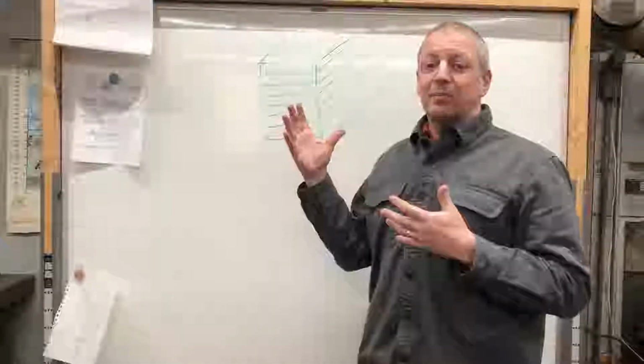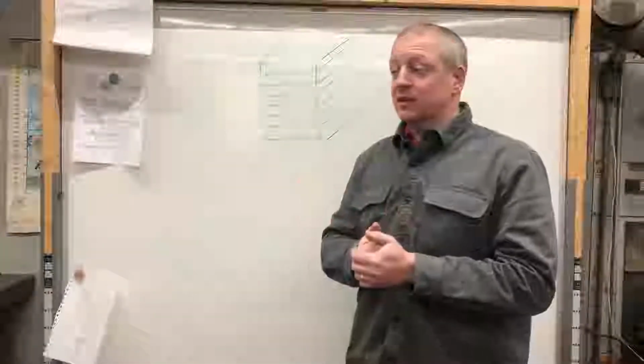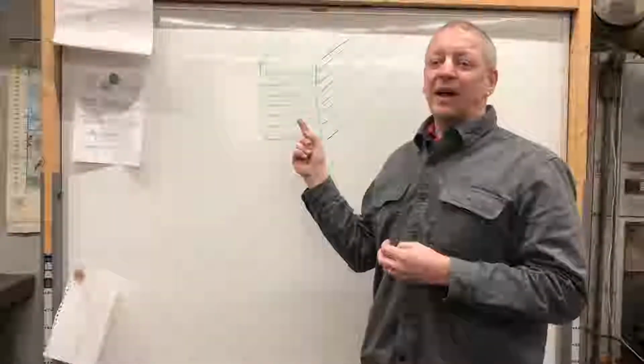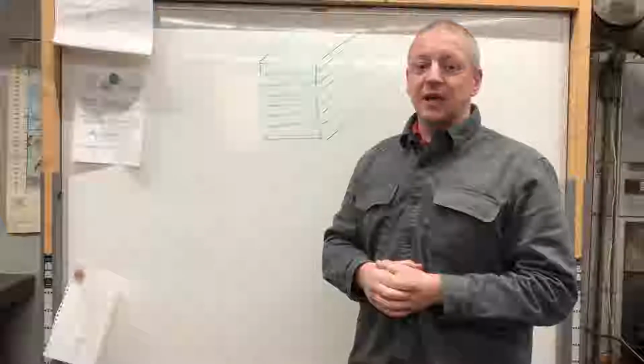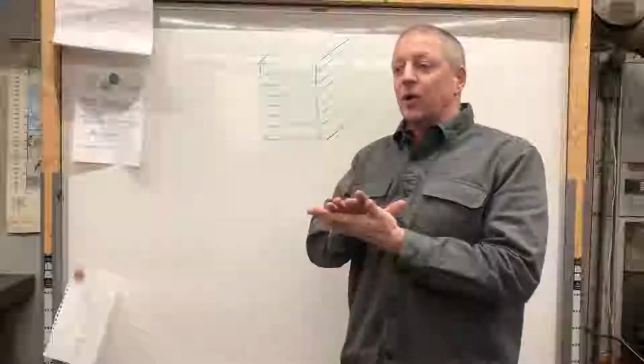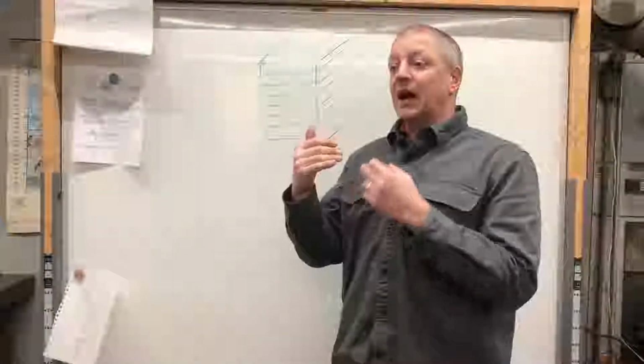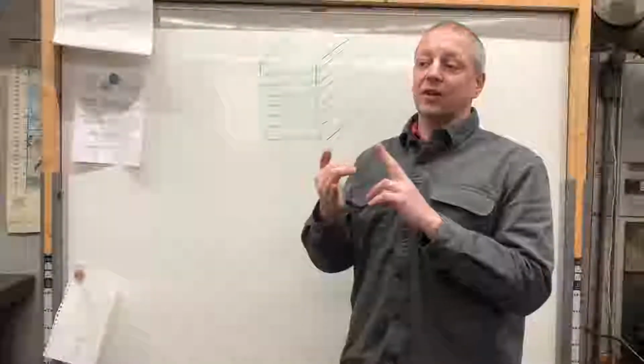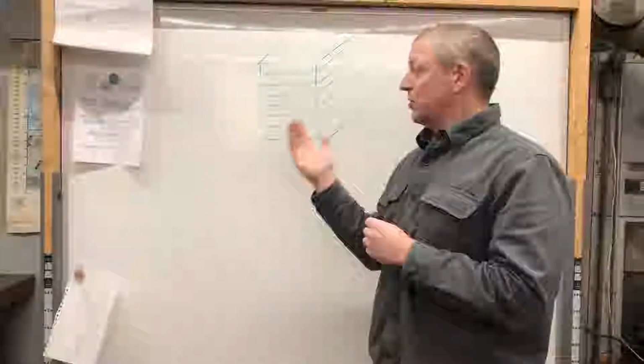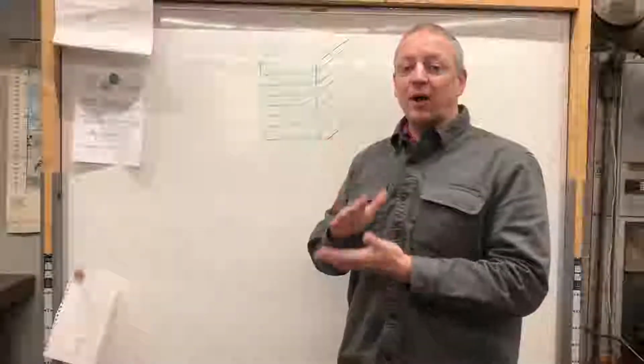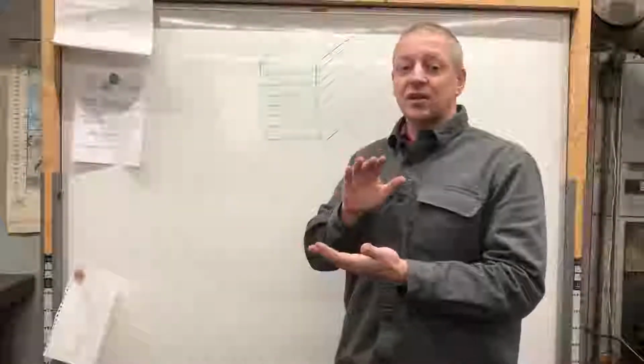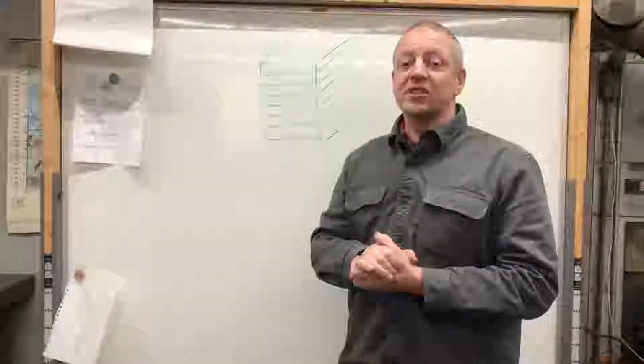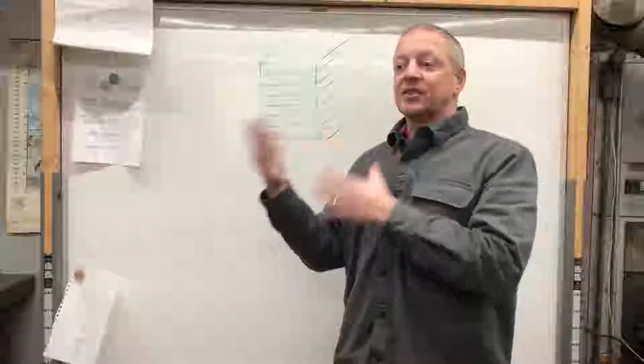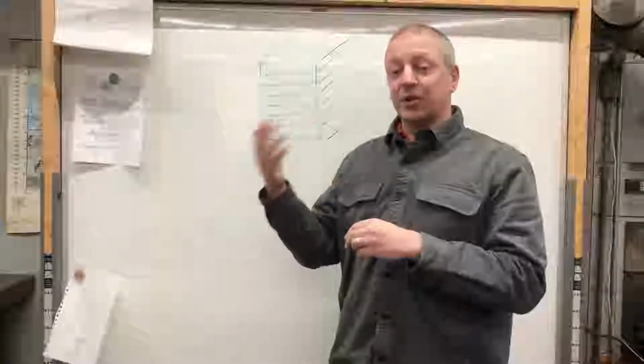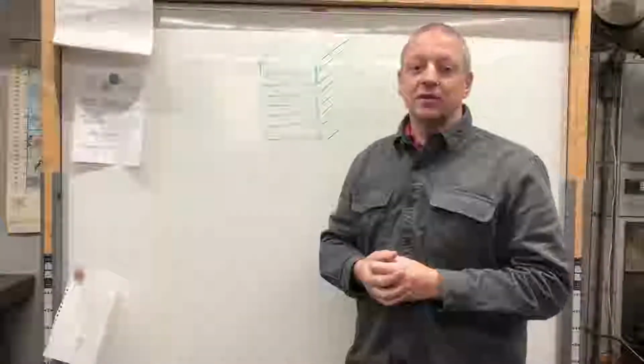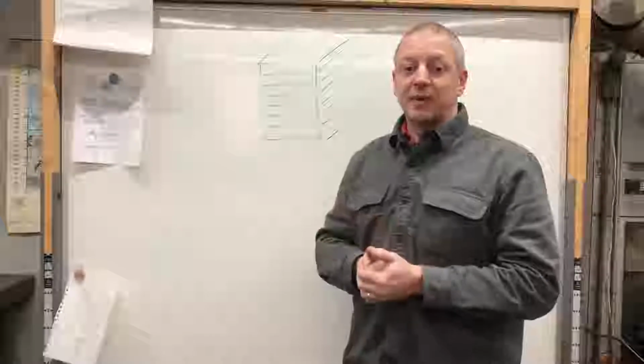So, what prevents a billet from welding? Essentially, if you have oxides in between your layers, those oxides will prevent the billet from welding. The higher the chromium content and the higher the nickel content of your materials, the harder it's going to be to get that weld to happen, because both nickel and chromium have very persistent oxides. This is why stainless Damascus, which we're not covering today, is so much more difficult than normal carbon steel Damascus.